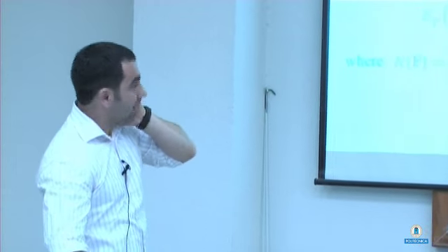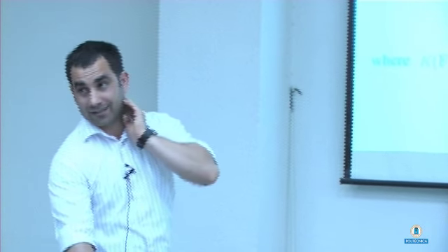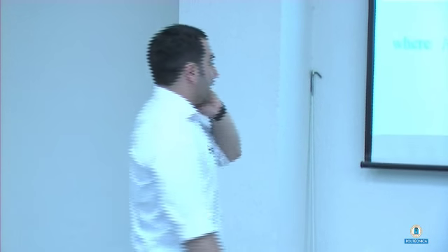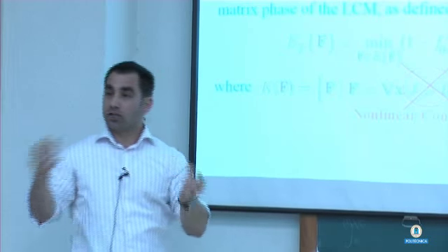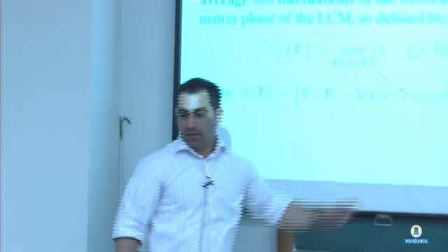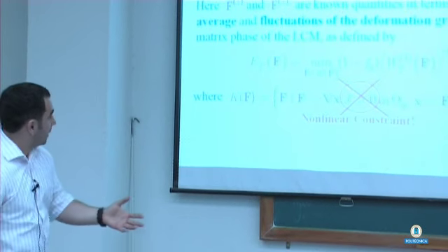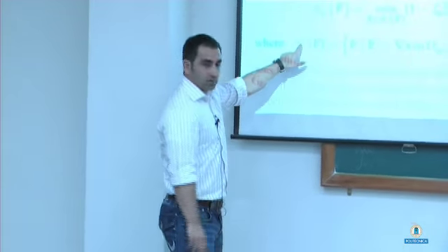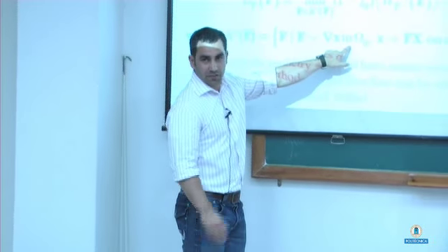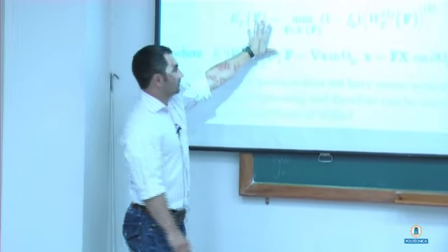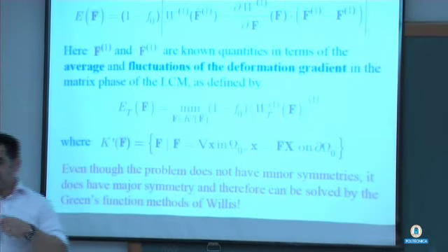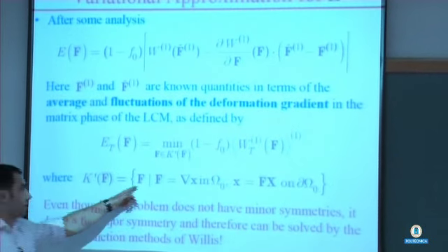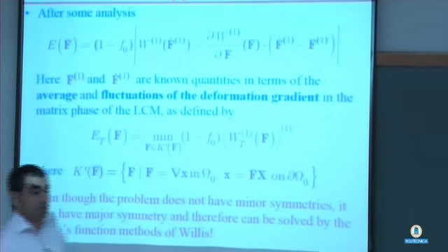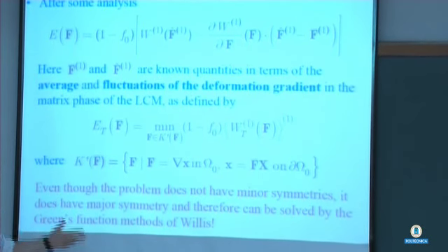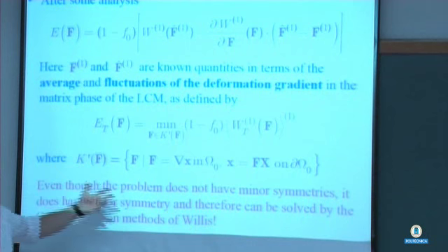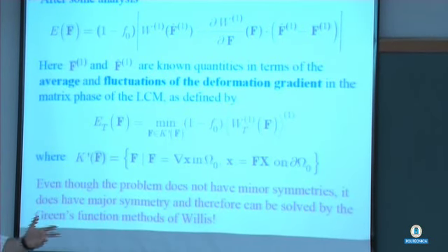So what we do is we enlarge the set, okay? So we're going to get rid of that, and we're going to make the set of admissible fields larger, right? So we're not going to impose the constraint. So we have a larger set. And basically, we denote that larger set K prime, no determinant. So now this is truly linear. And even though the stress and strain measures are non-symmetric, right? F is non-symmetric and the first Piola-Kirchhoff stress is non-symmetric. That doesn't really matter because it's linear, has major symmetry. You can solve this problem using Green's function methods developed by Willis, for instance, okay?